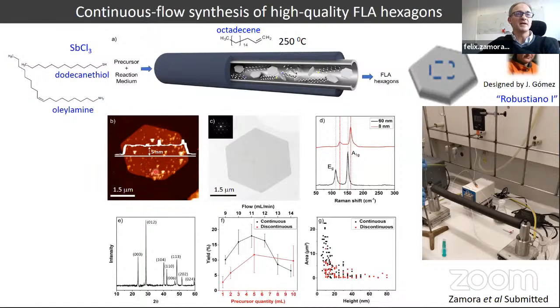Here, this is the AFM, telling you that you have relatively large dimensions. We were able to produce hexagons up to 6 microns in size, however with relatively small thicknesses, about 5 nanometers. As you can see here, they show nice morphologies. Eventually, this is the transmission electron microscopy characterization. Eventually, we have crystallinity. This is the electron diffraction coming from this hexagon. This is the Raman, confirming that we have antimony, few-layer antimony. And here, this is the X-ray powder diffraction, confirming crystallinity.